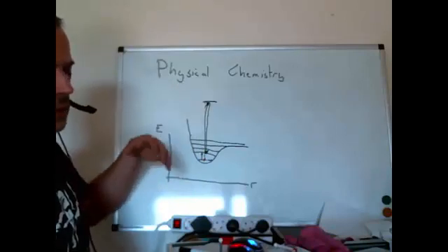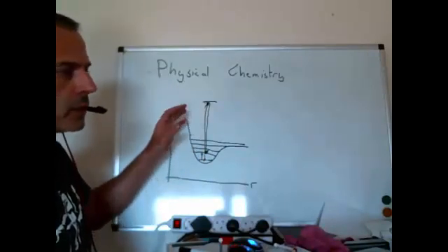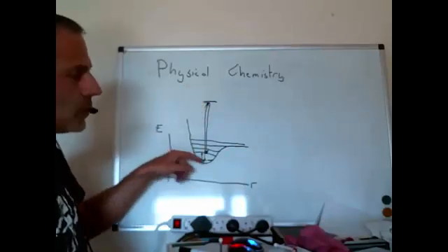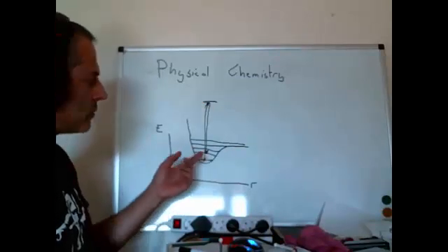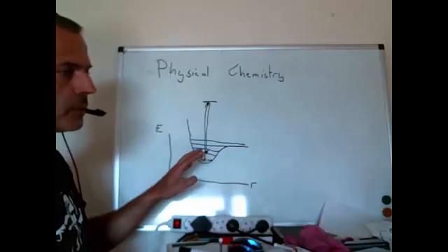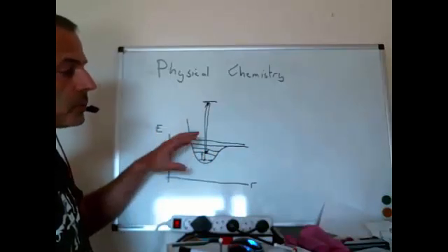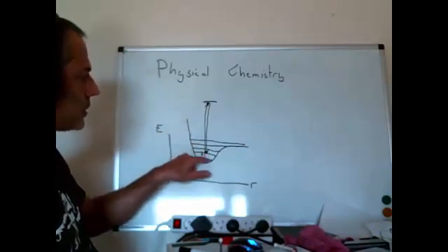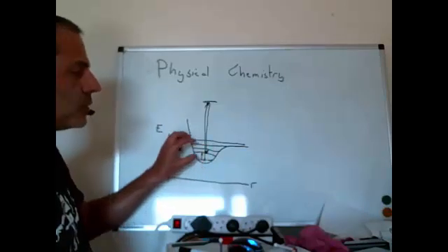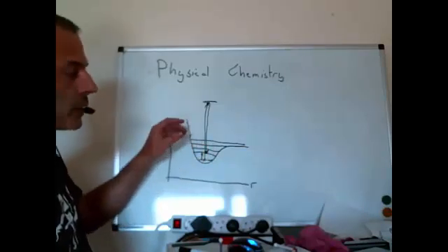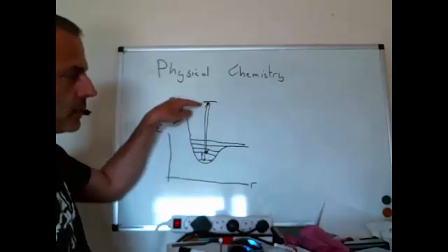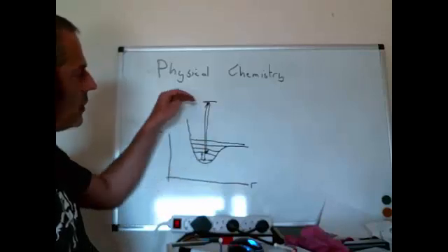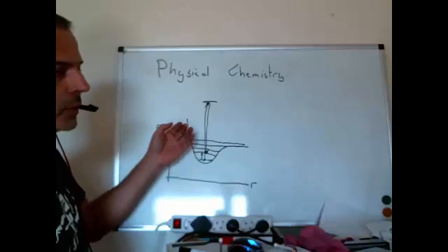But the probability is between 1 in 10 to the 9 and 1 in 10 to the 12. So most of the photons will be scattered, so they will go straight back down, and we get a very bright light of the color that we put in. So we need to get rid of that practically if we want to do this measurement. So we need a type of filter that cuts out one color very effectively, and we want to measure comparatively close to it because we've got an infrared transition. It's not very much energy, and very often in practice this is a red or green laser, so that it has a narrow color and a very high intensity, so that we can measure this very low probability event.